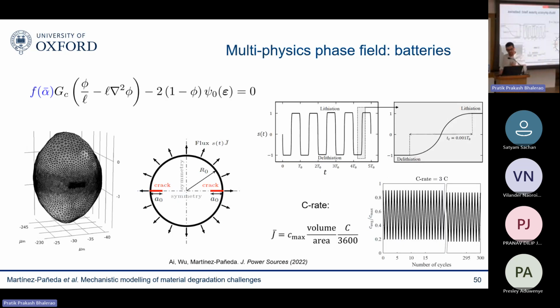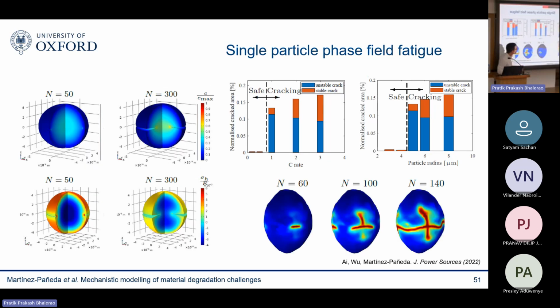And then what we did, a few groups have already worked on this with phase field, but they only look at a half cycle because they didn't have a fatigue model. So we had the fatigue, and we simulated hundreds of cycles, which is the scale relevant to these problems. And we modeled not only idealized particles, but also realistic particles, working together with people working on XCT scanning.